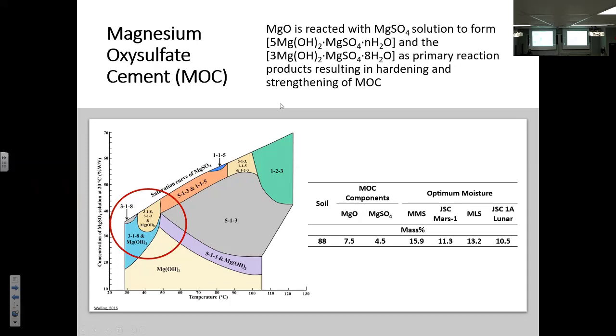And so in order to approach this whole consolidated soil sample, we decided to add 12% by weight magnesium oxysulfate components to our simulants. And then we add just the right amount of water. So you don't want your sample to be too mushy. You don't want to have a very dry sample. We call this an optimum moisture level, at which you can get maximum density. So the water level corresponds with overcoming any friction between particles. So when you compact it, you're getting the maximum density you can from a mixture.